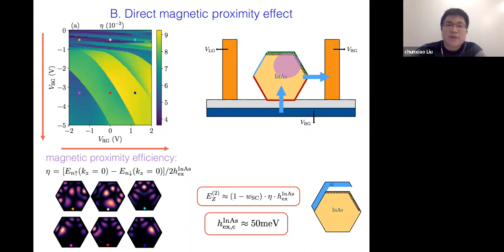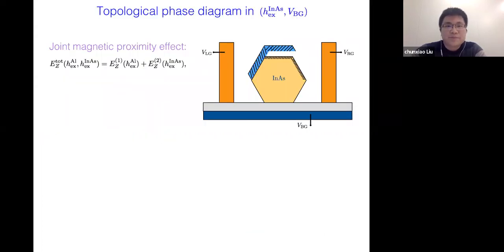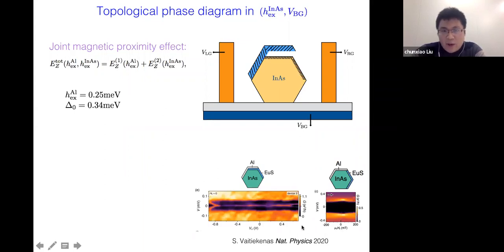And next, we will consider the joint effect of these two magnetic proximity effects and plot the topological phase diagram of the hybrid nanowire. Here, as I show, I consider both exchange coupling terms. We first plot the phase diagram as a function of the exchange coupling term due to the direct effect and the backgate voltage. And we fix the exchange coupling inside aluminum in this phase diagram. The chosen value is extracted by comparing with the experimental data. We can estimate this exchange coupling term by comparing how much the quasi-particle continuum gap is reduced relative to its bare value.